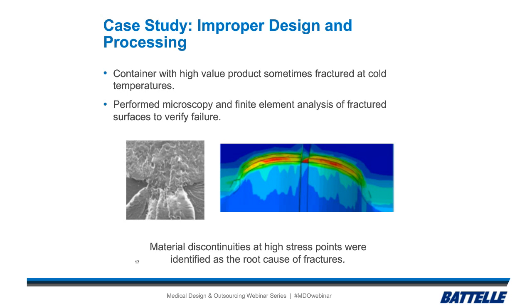And what we found is that the parison pinch point, so that point where after the extrusion is done, it pinches off, and then you do the blow molding, was not consistent. So that is the least consistent part of the container. The wall thickness there varied more than any part of the container, as well as the design for that jug, that was the highest stress point. So it had the sharpest corner. So that left picture is microscopy of that parison pinch point, and the right is an FEA image showing stress at that sharp corner.